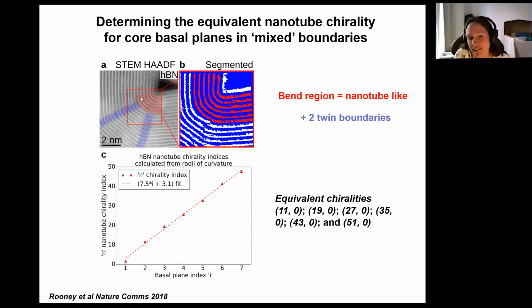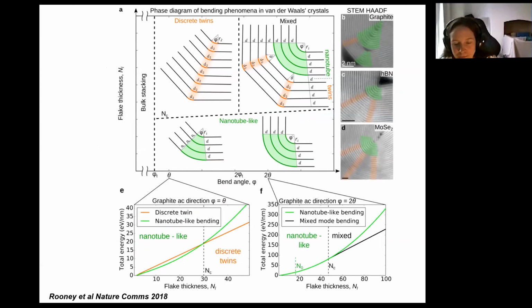So we can call this a nanotube-like bending region, where these regions don't maintain their stacking, but they have this expected nanotube-like curvature. And then as you get further away from the core of the bend, we again transition to these twin-type defects. So we're calling this the mixed type microstructure. You can look at the energy of these different microstructures and plot a phase diagram,